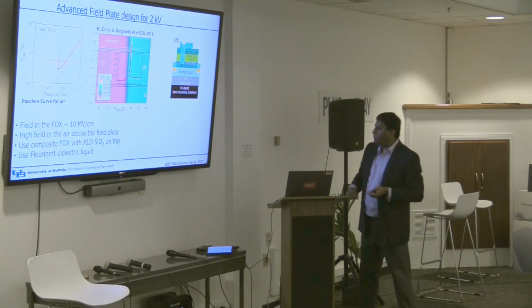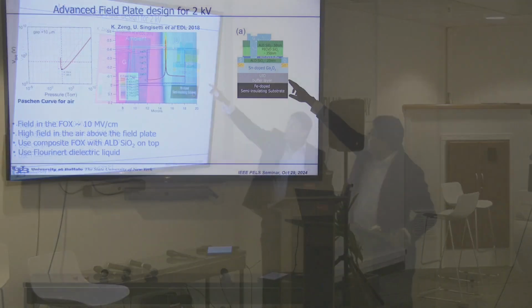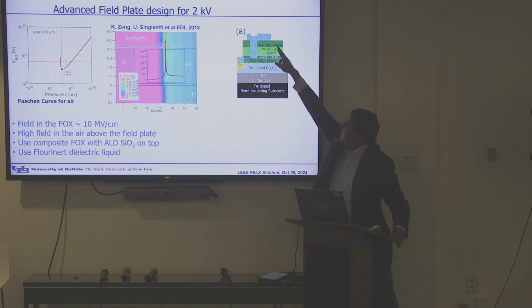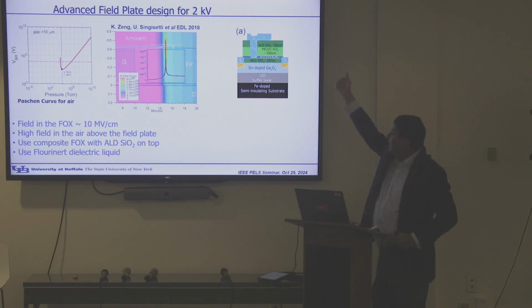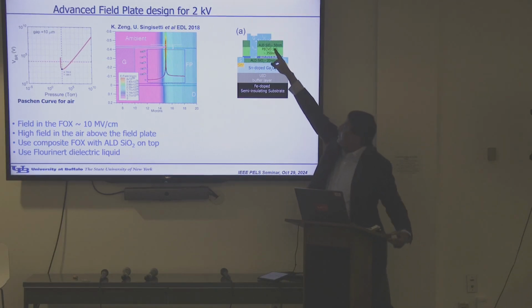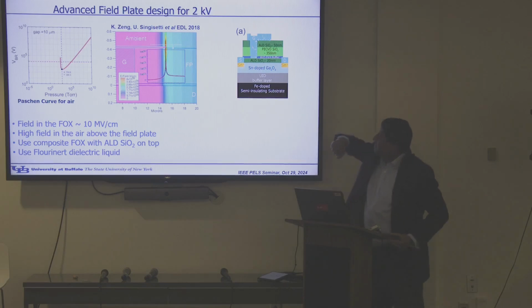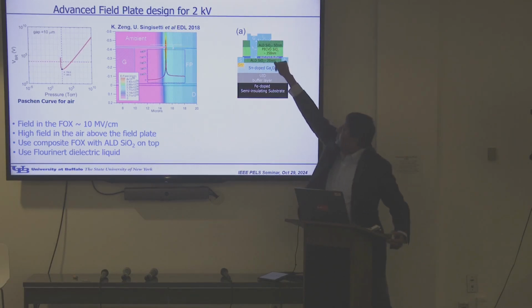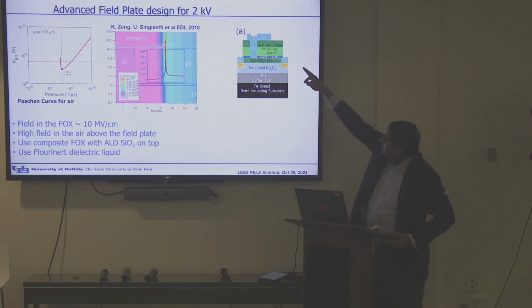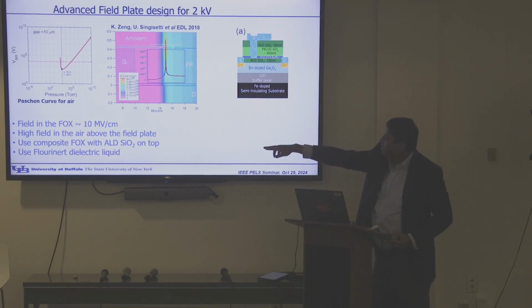So then we moved to a field plate design. You can see here what we do is we put a thick field plate. Again, it's a well-known technique in gallium nitride. So the field will move here, as you see in the center figure there, under the field plate edge, and then also on top. So we use Fluorinert dielectric liquid to measure the breakdown.